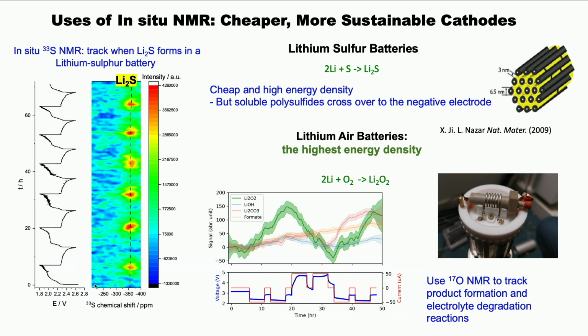Then just to move forward, we used our in-situ metrology to look at a whole variety of different materials. If we think about the next generation of higher energy density materials that are more sustainable, we could look at lithium sulfur, we could look at lithium air batteries. Lithium air is a reaction of lithium and oxygen to form peroxide. The problem with a reaction like this is that it goes via superoxides. Superoxides are basically radicals, the kind that inside the body cause cancer and will react with everything. They do the same thing in a battery: they will eat up the electrolyte and cause degradation. And so we've developed over the years oxygen methods to track what's going on. Similarly, we use sulfur NMR to track what goes on in sulfur batteries.